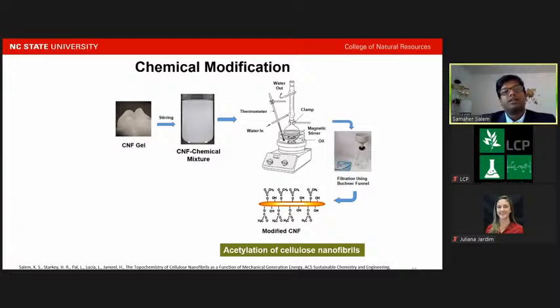Then I carried out the chemical modification, where I took the CNF gel mixed with chemicals, that is acetic anhydride, and I used acetic acid as a catalyst. I then put it on a hot plate stirrer and kept the temperature around 80 degrees Celsius and ran the reaction for an hour. The mixture was filtered and washed to remove the unreacted acetic anhydride after 1 hour, and we could get the modified nanocellulose.